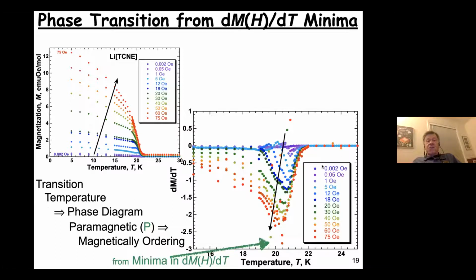Now we can also get some more information and determine the phase diagram for this material. And if we look at the magnetization as a function of temperature, you can see at different fields, they go up with increasing field. And if you take the derivative dM/dT, there's a minimum, and that minimum can be used to determine the phase boundary from the paramagnetic to magnetically ordered phase.